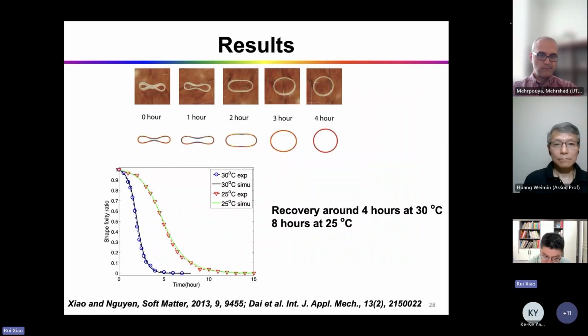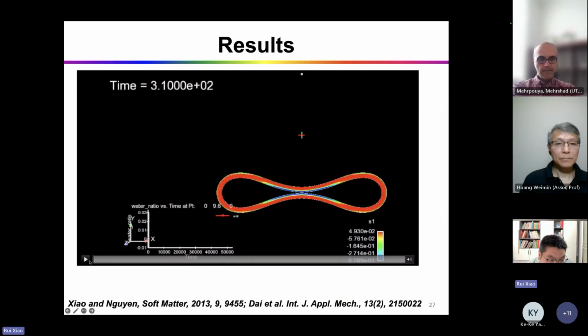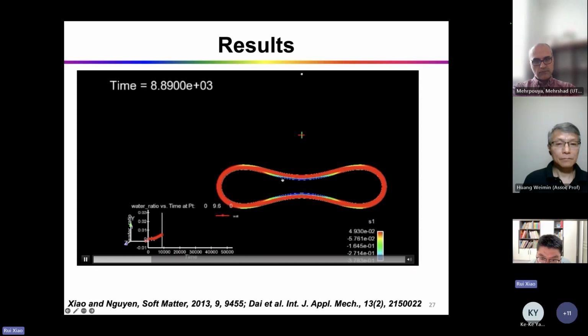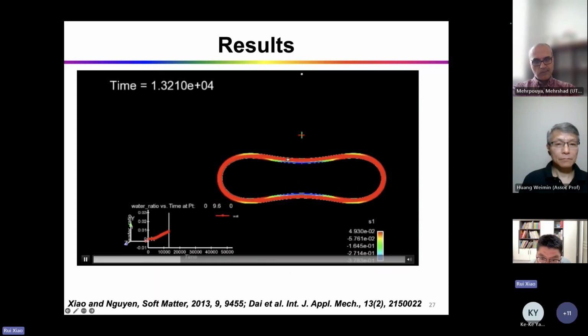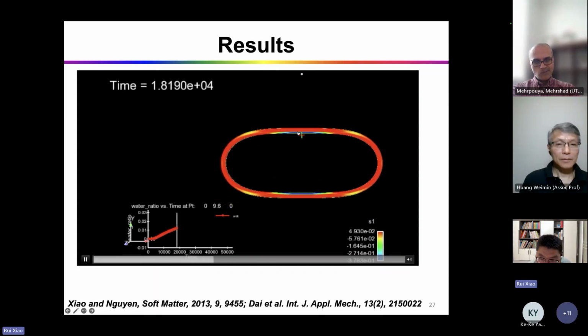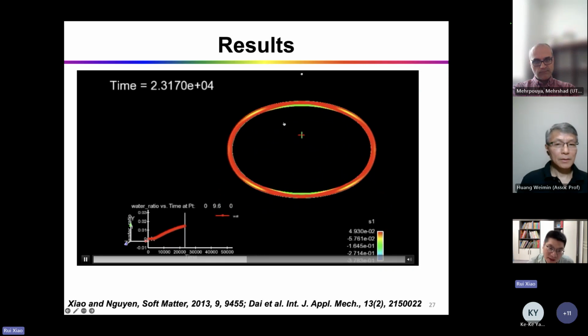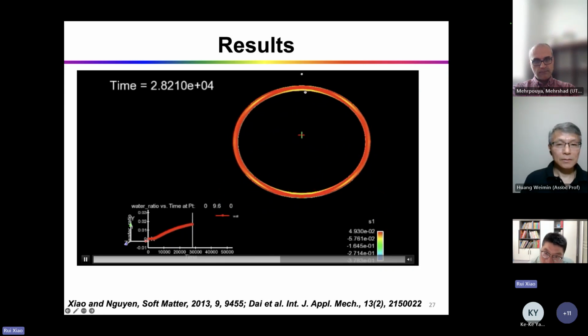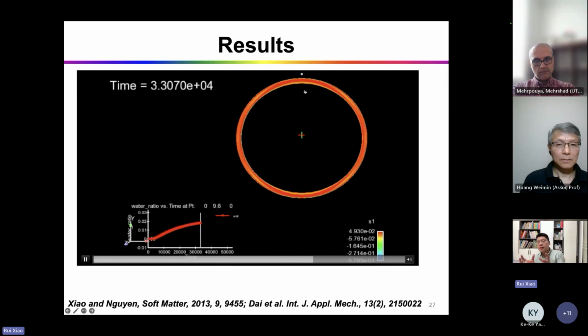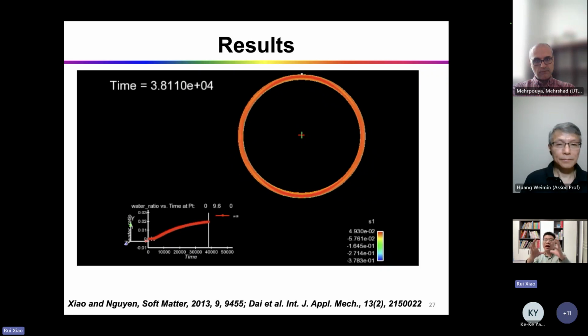For the diffusion process, you can see the solvent on the boundary is increased to the equilibrium value. It gradually diffuses into the middle side. So basically, as the solvent diffuses into the polymer matrix, it softens the material and the material can recover.